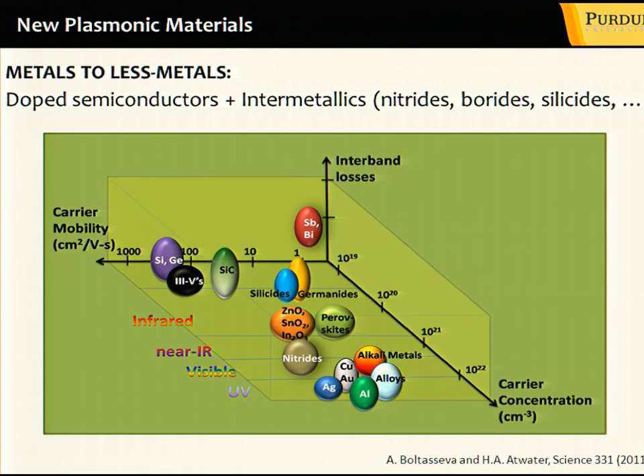And just to give you the idea why we have this problem, with silver and gold, which are normally considered to be the materials of choice in terms of plasmonic materials, the plasma frequency is actually very high. It's 9 eV. To get negative dielectric permittivity, and that's what actually makes a material plasmonic, the frequency should be smaller than 9 eV. But 9 eV is really deep ultraviolet. It means that when you go to, for example, telecommunication wavelengths, your dielectric permittivity becomes extremely large in magnitude. Minus 100 or even more, much larger in magnitude than the dielectric permittivities of the dielectric components which you typically use together with metallic ones. So they're kind of mismatched, and it's hard to make materials with a balanced effective dielectric permittivity.